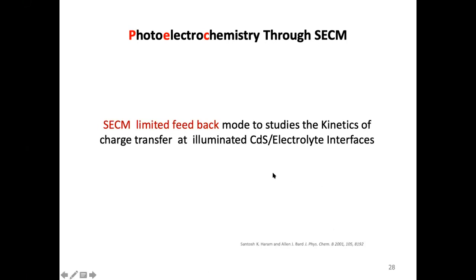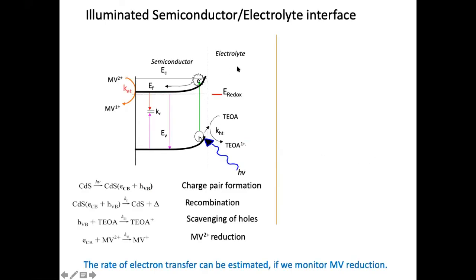Here we have chosen the cadmium sulfide electrolyte interface. Some of the physicists or chemists also know that if you immerse a semiconductor in a redox solution, it gives this kind of band bending. It in fact forms a Schottky junction. Now if you illuminate such a junction with light whose frequency is higher than the band gap, what will happen? It will form an electron-hole pair. It's called charge pair formation. Electrons go inside because lower energy is there, and holes bubble out.